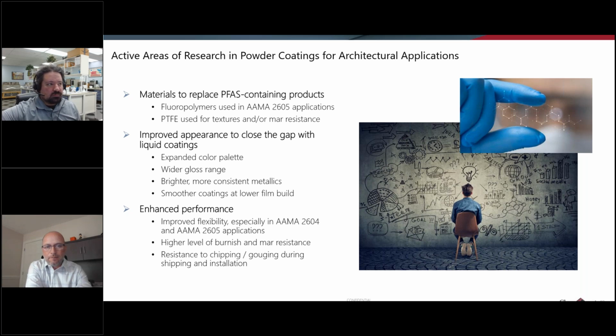are fluoropolymers. And then we also didn't talk about it, at least I don't remember talking about it, PTFE or Teflon materials are used a lot to create textured powder coatings, and also to modify for mar resistance and scratch resistance, mostly mar. Now, without getting into a debate about what should happen or what we believe is going to happen, what you need to know is people are not taking the risk of not doing anything. So coating companies and raw material suppliers are trying to find materials that could replace these, which is much easier said than done. But at any rate, there's a lot of active research on PFAS-free materials or materials that don't contain any fluoro, because they may eventually become called PFAS-containing materials.